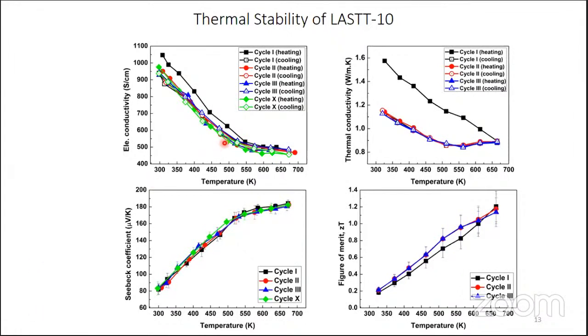So for this result, 10 times we measured, 10 times we cycled the material, heated up to 700 Kelvin, and saw how the electrical conductivity and the thermal conductivity of this material vary. But to our surprise, we found that, in fact, we did both heating and cooling. We did not measure only during heating, we measured during both heating and cooling. In the first cycle, when we heat and cool, there is a difference in the electrical conductivity between the first cycle and the remaining cycles.